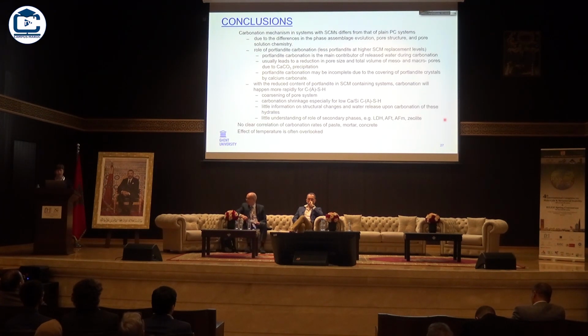So to conclude, for this literature review, the carbonation mechanisms in systems with supplementary cementitious materials are different from those of plain Portland cement systems. You have differences in phase assemblages, pore structure, pore solution chemistry, and very important here is the role of the Portlandite carbonation, because with these SCMs you will have less Portlandite available. What does this mean? Less buffer. It's also the main contributor for water release during carbonation.